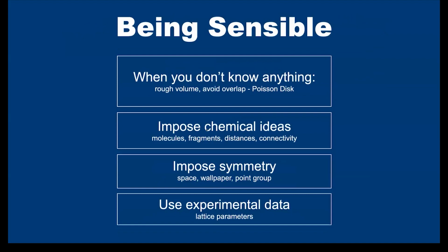Now, one detail is that when we're making these random structures, they're not, in some sense, completely random. Completely random doesn't really make sense because you always have to draw from some distribution. So when you're making a random structure for a crystal structure, the first thing you'll realize is you have to draw from a distribution of unit cell volume sizes. Are the lattice vectors in angstroms, kilometers, or light years? Well, they're going to be in angstroms. So we choose from a distribution that goes over a range of angstroms and doesn't have very, very large unit cells. If the unit cell was very large, the atoms would never find each other. You just have a gas, or a very, very dilute interstellar environment in the light years case.